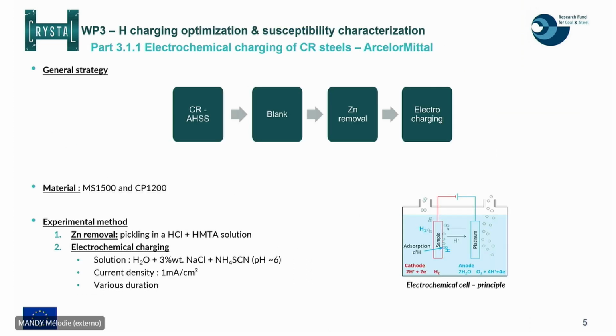So let's begin with the hydrogen charging of the cold rolled steels. Here we come back to the general strategy that Sílvia has shown you very briefly during her presentation. In this case, for the cold rolled steel, we have performed electrochemical charging. This was decided to be representative of what is done or what can appear in the industrial reality. In the case of cold rolled steels, when we received them, we were first forced to remove the zinc coating as those materials were electrogalvanized, and then perform the electrochemical charging. This was performed mainly at ArcelorMittal for 2 different grades, the MS 1500 and the CP 1200.